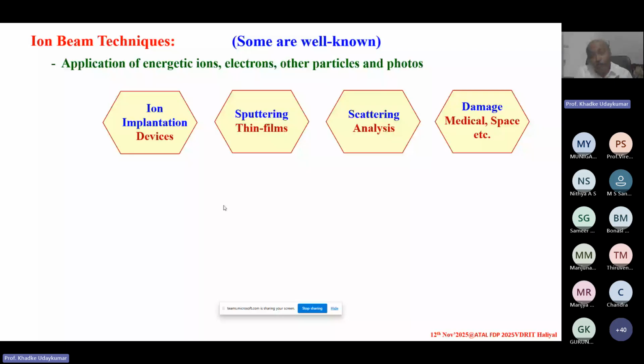But before penetrating the inner side, when it is hitting the surface, there is always a possibility that some of the ions get reflected back, or the atoms sitting on the surface get sputtered on the upper side. So sputtering is nothing but erosion that you are creating on the surface. The erosion will be created with very fine structure, of the order of a few nanometers only. That is nothing but nano patterning. So sputtering of the ions from the surface of the thin films, due to sputtering, you will be able to create nano patterning on the surface.